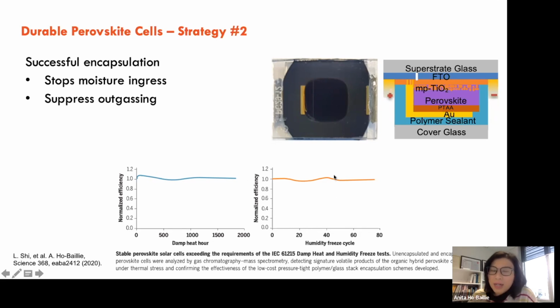And we're able to make our cells pass the industry standard tests. There are a few industry standard tests where we torture the cells, for example, thermal cycling between -40 and 85 degrees. We don't have a lot of time to sit around and wait for the cells to die in 25 years, right? So we accelerate the environmental effect by putting them into environmental chambers and cycling them through the temperature extremes. Or we put them into environmental chambers with high humidity, 85% relative humidity, and high temperature, 85 degrees Celsius, and see how long they will last.